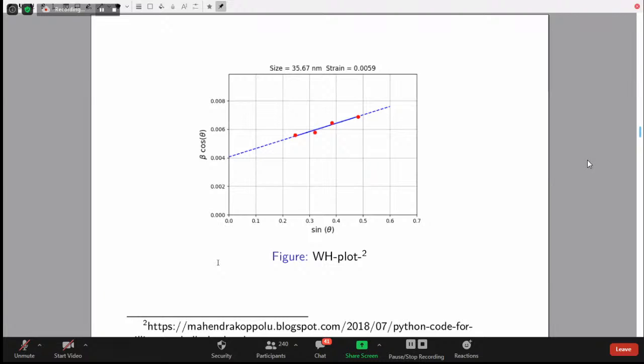How this goes is, the effect of strain should be propagated throughout the sample, or is this strain there in one particular crystallite alone? Means the crystallites which are oriented in one particular direction are the only ones experiencing it. So it depends on which peak you have chosen to analyze. So what people have done is, instead of getting confused with the different peaks, let us analyze everything in a single pattern. That is something people call whole profile fitting. Okay, Professor, they use all the peaks to do that. But what I explained till now, Scherrer as well as Williamson-Hall, is peak by peak.